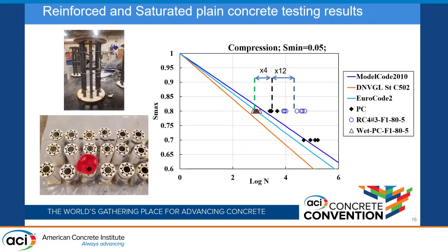We then examined the effect of saturation and the effect of having longitudinal reinforcement in the cylinder specimens. We put some plain concrete into water, and after a few months tested them. Saturation decreased the fatigue capacity by four-fold, while the reinforcement increased it by 12-fold on average.